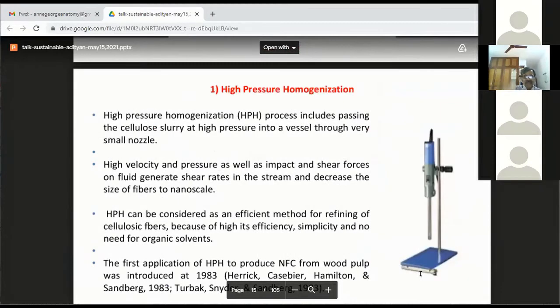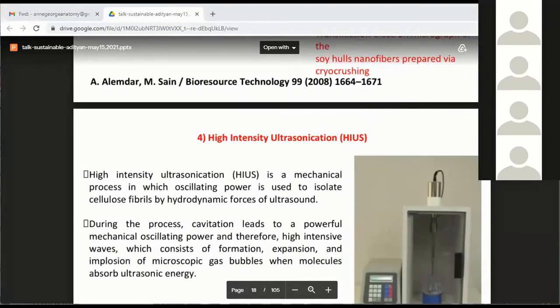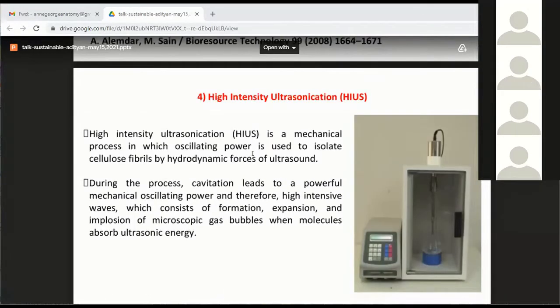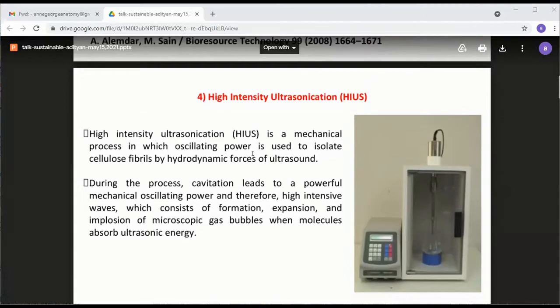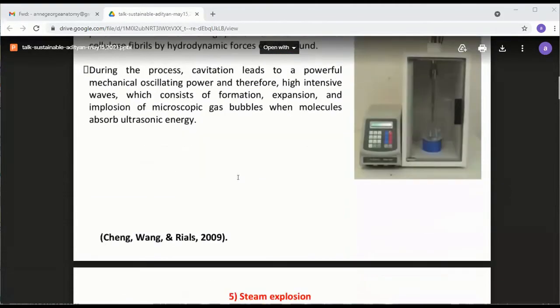What do they do? If you look at high pressure homogenization, the process includes passing the cellulose slurry at high pressure into a vessel through a very small nozzle. And you subject this nanocellulose to very high shear forces. And because of high shear forces, you can fibrillate, you can get nanoscale. Look at the super grinding process invented by Japanese colleagues, Professor Abe, Professor Iwamoto. You can see this Biomacromolecules paper. The next method is high intensity ultrasonication process. There also you apply high shear force and then you come to nanoscale.